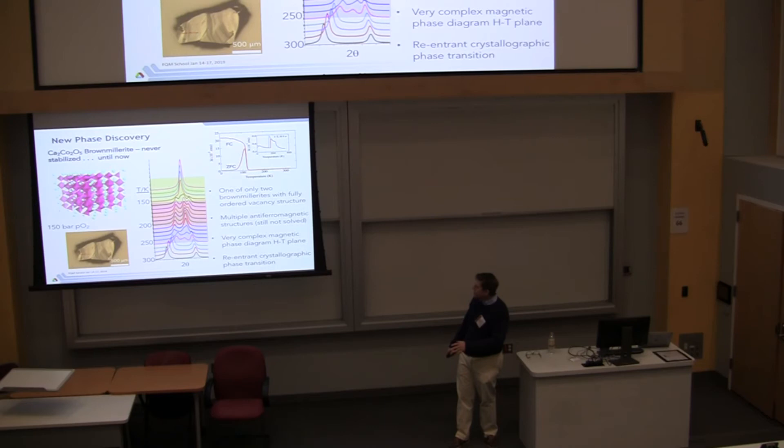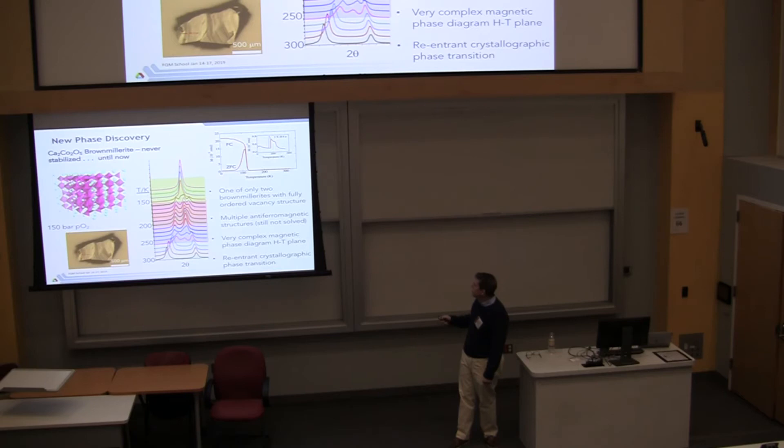Now it's pretty close to the liquid. It's 100 bar. It's not very far from 150. It's some calculation with who knows what parameters are in there. And the shift in temperature of this line with pressure is logarithmic. So it's kind of dicey whether it's gonna work or not, but it gave us enough impetus to try it. Right? So we tried it and failed. Okay? We did not make that material. We discovered a new material. Right? So we discovered calcium 2 cobalt 2 O5, which is a brownmillerite.